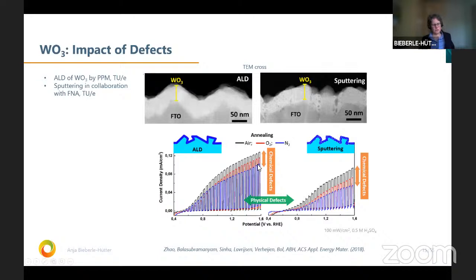So actually we wanted to get better performance, and the first layers were annealed in air. And then we thought, yeah, if we go to O2, an oxygen-rich atmosphere, perhaps we have less vacancies, perhaps we get higher performance. And we repeated all these measurements for the sputtering several times. We always got a better performance with the air annealed than with the oxygen annealed, and for sure with the nitrogen annealed, it is lower.